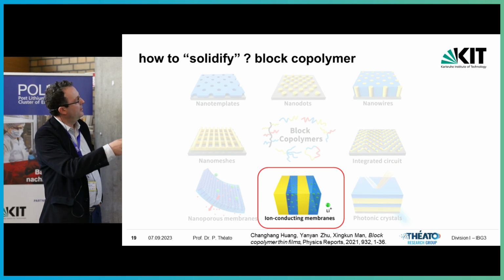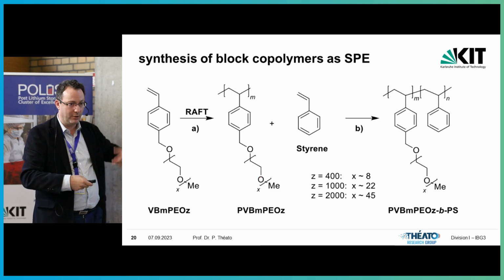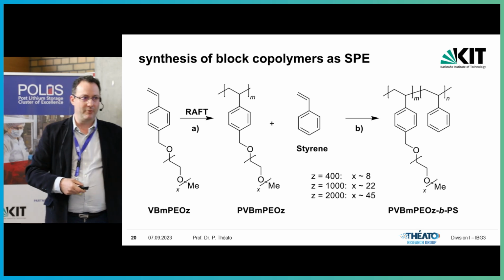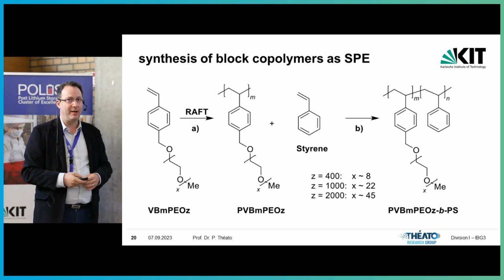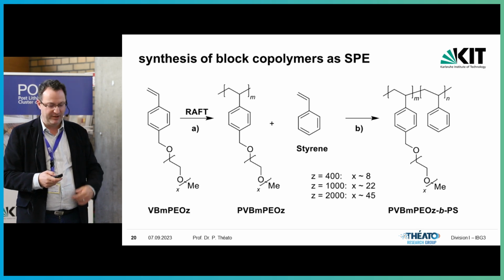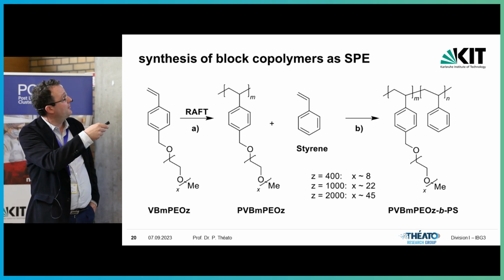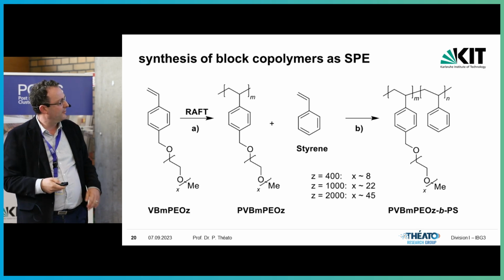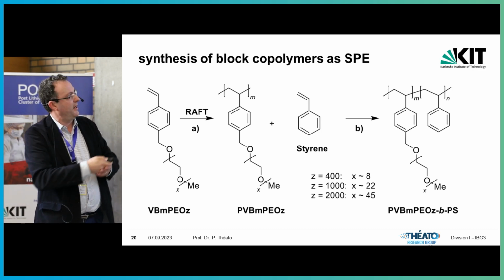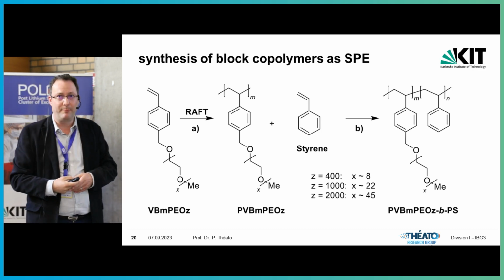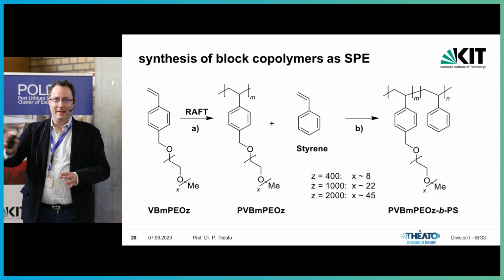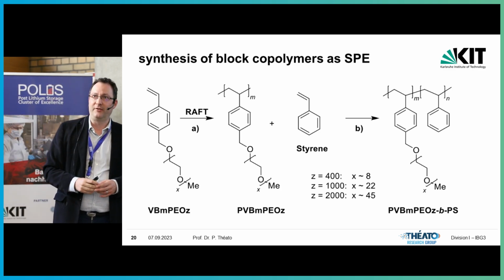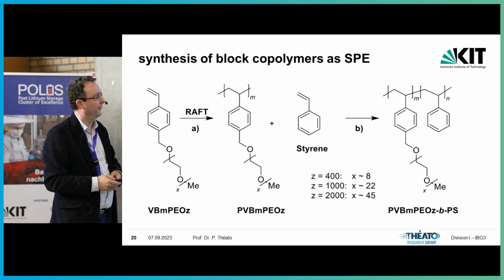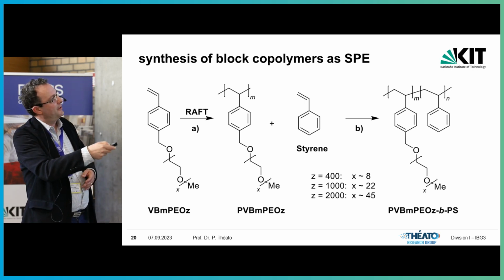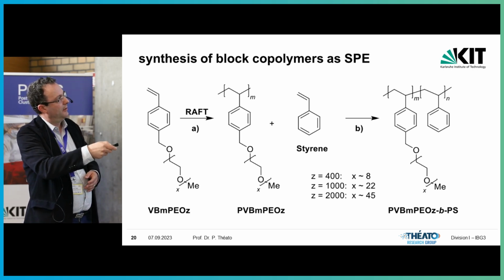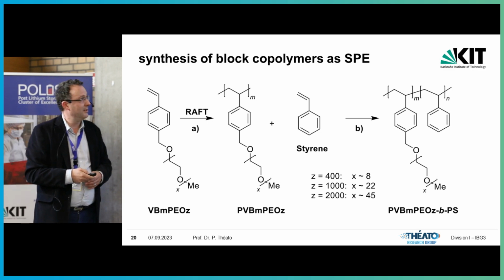So what we do is we use a PEO side chain system. We learned a lot from the first project. We learned that the vinyl ethers are nice to make, but not really the most feasible system. So we changed to styrene-based systems, again all ether-based, and then styrene as a second block, because this has a glass transition temperature around 100 degrees centigrade. So anything up to 90 plus degrees centigrade, we have stable films. So we get a diblock polymer: an ion conducting block and a mechanical stabilizing block.